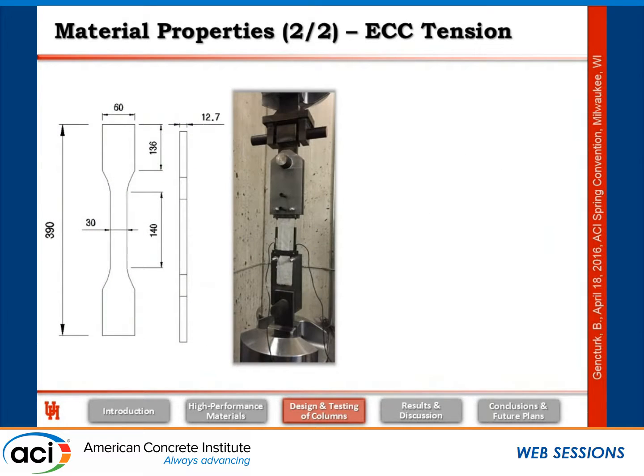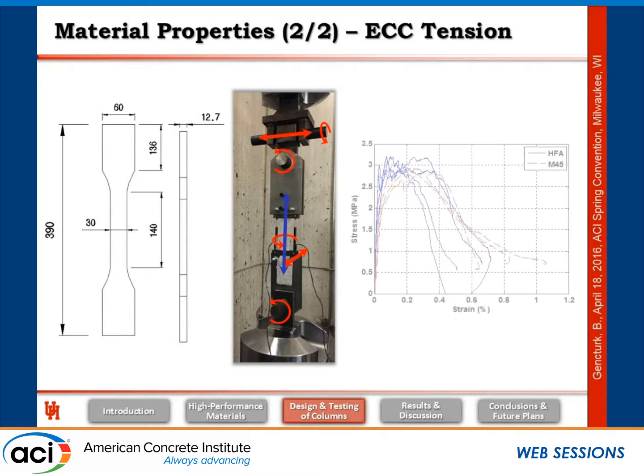So this is the ECC behavior in uniaxial tension. Testing any cementitious materials in tension is tricky because they're very brittle. Even if they go up to 3-4%, you need to make sure that you're really applying uniaxial loading rather than bending or torsion or anything. So we came up with this design that was basically releasing all the other degrees of freedom so that we end up with only the axial degree of freedom. You can see this, we are missing one plate here so that we can show you the specimen here. And then we made this just a uniaxial test.